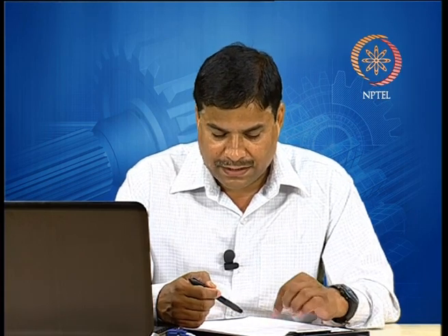For the first stage, in the case of a smooth component, some sort of crack will nucleate at any point where stress raisers are present, either in the form of a defect or a surface irregularity like greater roughness. In other cases where some sort of discontinuity is already present, those discontinuities and sudden variations in the cross section will act as stress raisers, facilitating easy nucleation and growth of cracks. So what is the difference in how fatigue life will be affected in the two cases, when one has discontinuities and sudden changes in cross section, and the other has a very uniform cross sectional area and smooth finished surface?